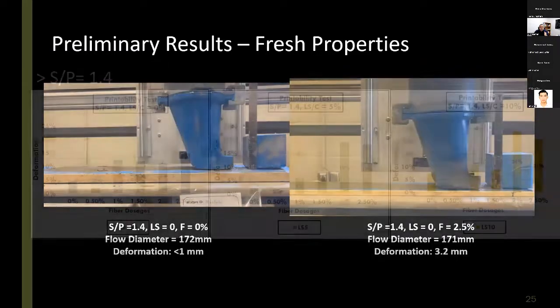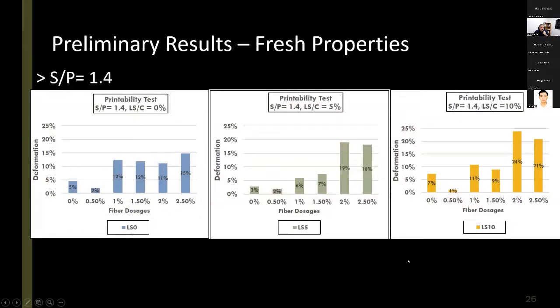And here are the actual data that we collected for the layer deformations. Here, these are all the mixtures at sand to powder ratio of 1.4 at different dosages of limestone. And looking at each graph, you can see that as a general trend, higher dosages of steel fiber gives us more layer deformations, which is not good, of course. And also, we don't see significant improvement, at least, in the layer deformations by addition of limestone powder.